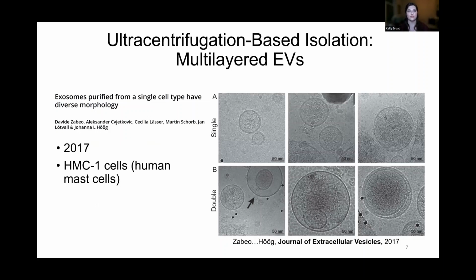They found multi-layered morphologies to be present in relatively low quantities, but familiar morphologies from the prior studies are present, such as the high electron density EV with a smaller asymmetrical EV inside and concentric lipid bilayers.